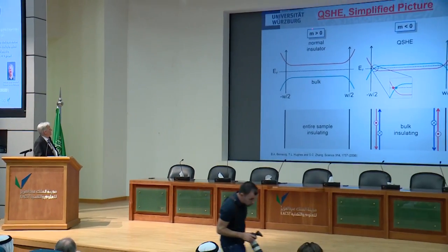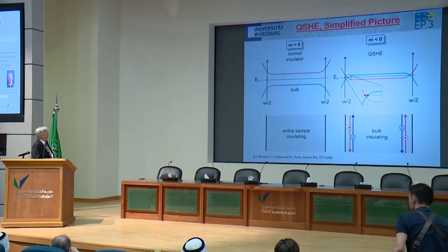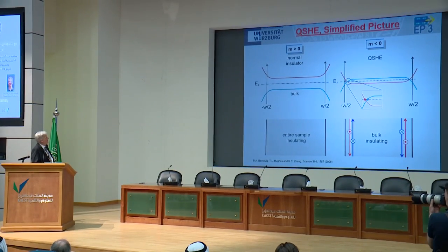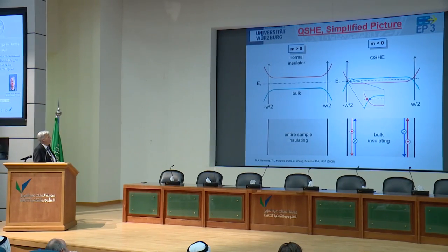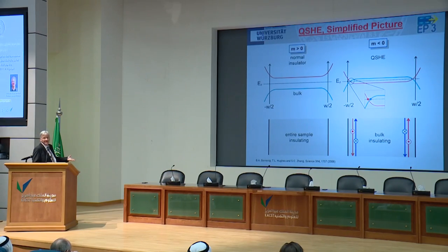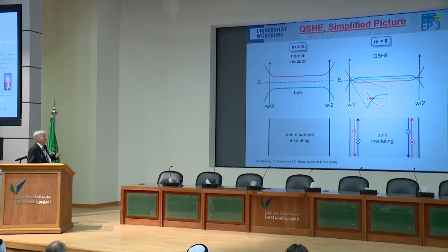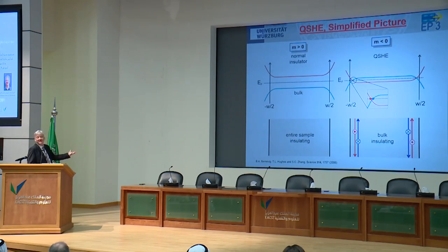But look now at what happens if I do the same thing with an inverted material. In this normal material, if the Fermi energy is in the gap, well, I don't hit any dispersion, so I have no conductance. But now, in my quantum spin Hall material, just my inverted semiconductor, basically I have a conduction band that at the outer side realizes that in the topology of the outside world, it is a valence band and it has to bend downward. Like this here. And the valence band realizes it's a conduction band and bends upwards. So if I now adjust the Fermi energy in the middle of the gap, now you see that I cross these dispersions, meaning that I can have charge transport at the edges of my material.